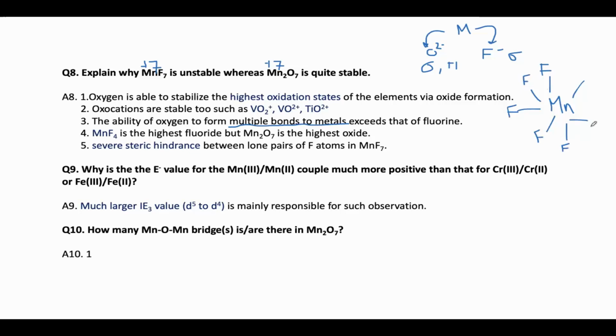You all know that a metal-fluorine bond is very short. That's why all the lone pairs of electrons will be close together. And since the fluorine atom is also small in size, all these lone pairs of electrons will cause severe steric hindrance among these fluorine atoms. This lone pair repulsion will actually destabilize the entire system. Since the atoms are smaller in size, they will be dragged more towards the manganese center, so that will cause severe steric hindrance between these lone pairs of the 7 fluorine atoms. That's why in case of MnF7, the system is actually getting destabilized, which is not that prominent in case of the oxide species. That's why MnF7 is unstable.